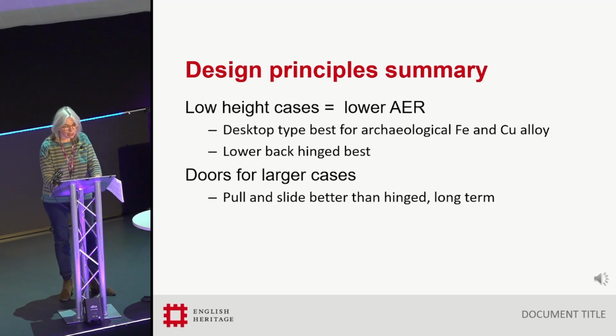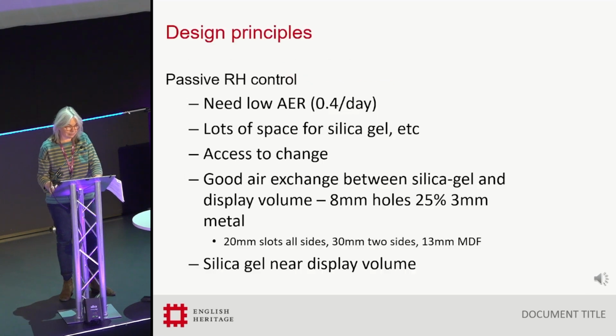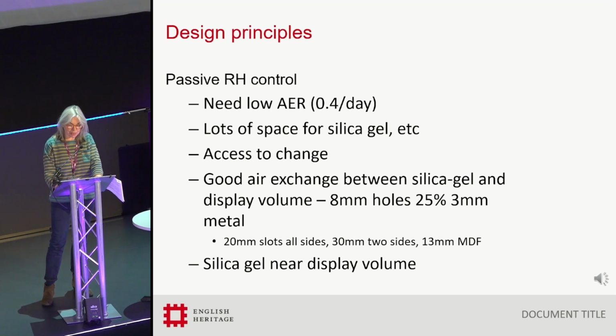So to summarise, low height cases equal lower air exchange rate. And a desktop case is best for archaeological iron and copper alloy, and a lower back hinged case top is best. If you use larger cases, pull and slide doors are better than hinged long term. And for passive RH control, you need low air exchange rates, so 0.4 a day. Lots of space for silica gel, access to change the silica gel without interrupting the case display volume, and good air exchange between silica gel and display volume.